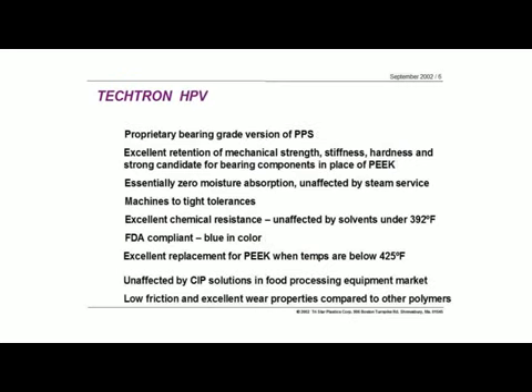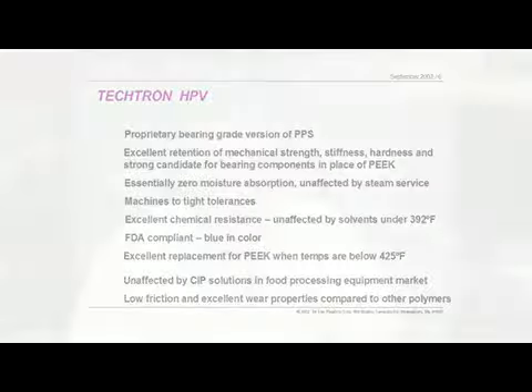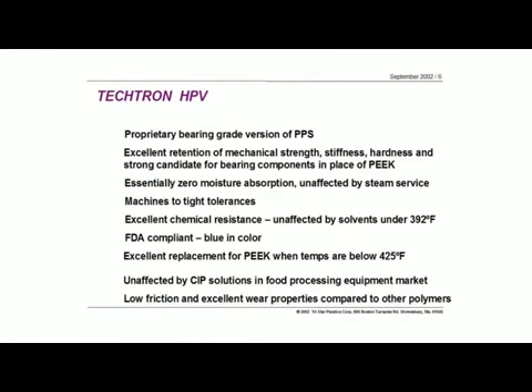Now the Techtron HPV, which is the bearing grade version, is unique in terms of its makeup. There are other bearing grade PPSs out there, but the HPV material from Quadrant is unique in how it's made in terms of its fillers. Again, we get all of the very strong mechanical properties, and so for a bearing application, again, with the temperature being the driving force here, it's a very good material to replace bearing grade PEEKs if the conditions warrant. The zero moisture absorption, steam service holds true for the HPV.